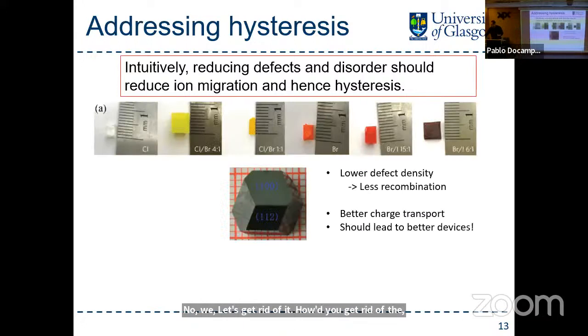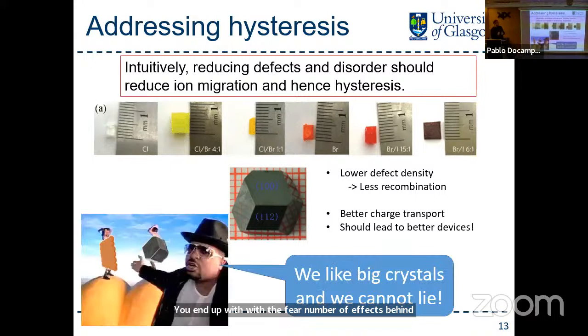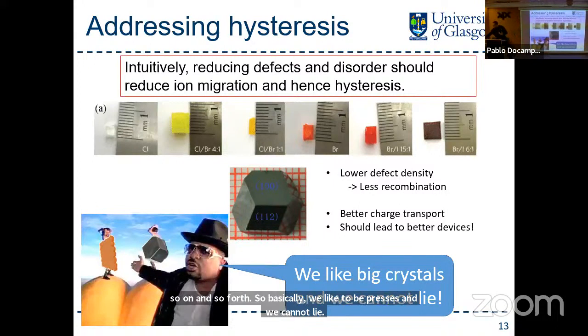Let's get rid of them. How do you get rid of the ions? Well, the easiest, particularly for chemists, is to just make bigger crystals. Normally, slow down the crystallization, and then you end up with fewer defects. If you end up with a single crystal, ideally, you end up with a fewer number of defects with ions, and so on and so forth. So basically, we like big crystals and we cannot lie. So we're always trying to minimize the ions.